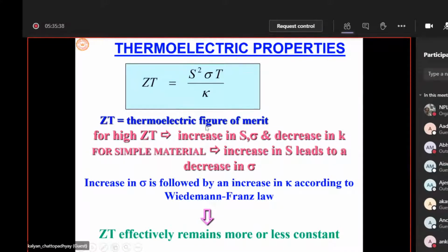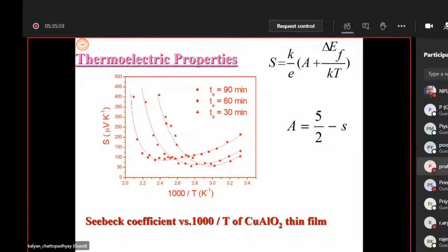Now this delafossite class basically satisfies this criterion inherently, because in the ab plane the carrier density is higher and the c-axis is much larger, so you have anisotropy in the system, and independent variation of sigma and K is possible, and large ZT is of course possible. And we showed that more than 400 microvolt per Kelvin Seebeck coefficient could be achieved in such material.